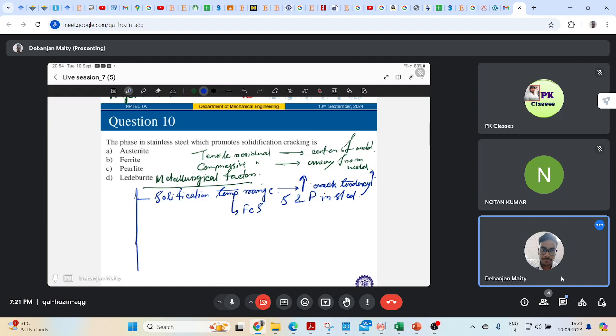Now, that is one factor, the solidification temperature range. If you have some eutectic reaction, that will also happen during the terminal stage of solidification. You'll always have some eutectic reaction. I have shown you what is eutectic. If there is a eutectic reaction taking place, that will also extend the solidification temperature range. Those are mostly common in aluminum alloys. So this is one, sulfur and phosphorus. Eutectic reaction also will increase your temperature range. That will also increase your solidification cracking.